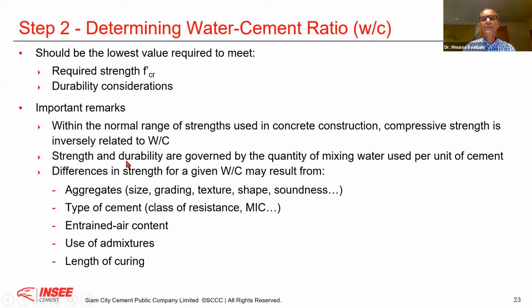Also, the strength and durability are governed by the quantity of mixing water used per unit of cement. This is why I say, you know, very often people put too much water. Therefore, if you have some negative effect, it is not because it is sometimes the cement or the aggregate, but because you put too much water. And difference in strength for a given water cement ratio may result from the aggregate. Yes, if you don't have sound aggregate, you have flaky, a really bad shape, or the type of cement you use is low, like 32.5 strength class instead of 42.5, for example.